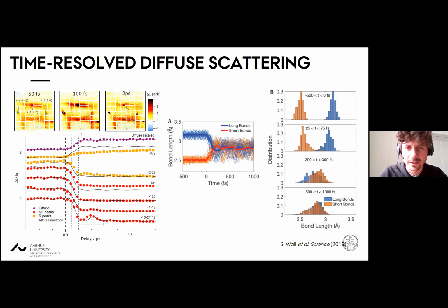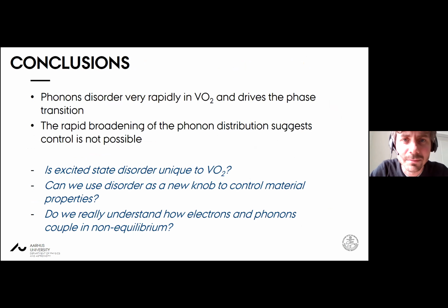Okay, that brings me to my conclusions. I think I've gone a little bit fast actually. It shows very clearly, I think, that vanadium dioxide is driven by phonon disorder in the system. This is in a way quite challenging, because it suggests that this disordering in the phonons means that we can't reverse this phase. What would be nice in vanadium dioxide, and in many systems, is not only the ability to go from one phase to another, but to be able to bring it back. And reversing a disordering type of process is much harder than reversing a nice coherent process.